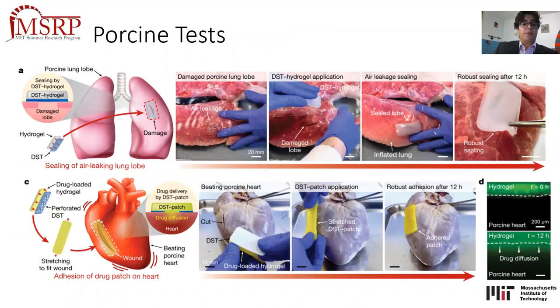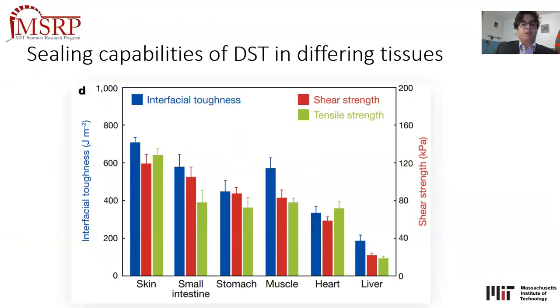Durability of the adhesive depended on whether gelatin or chitosan-based DST was used: gelatin for a durability of weeks and chitosan for a durability of months. However, adhesion capabilities may vary in tissue type adhered by the DST. This is why variables like interfacial toughness, shear strength, and tensile strength were measured.